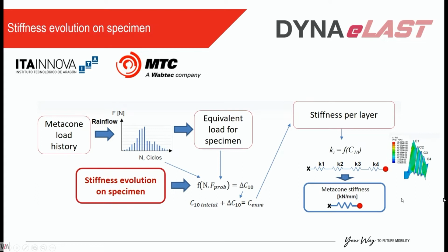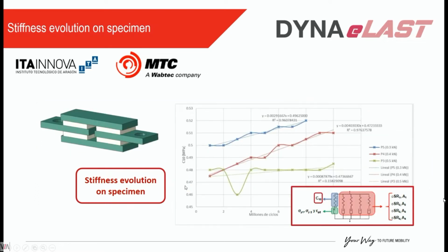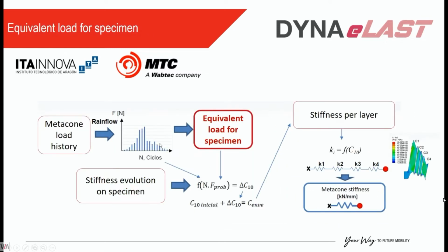So for the stiffness evolution of the specimen, we use a quadruple shear specimen. Like I said, the model of the material is actually rather complicated. I won't go into the details because I don't understand them, but we have an elastoplastic branch, we have a viscoelastic branch, but we only take into account the evolution of C10 in the hyperelastic branch. So we can track it as a function of the cycles being applied. It changes with the amplitude of the cycles and with the preload that the element is subjected to.